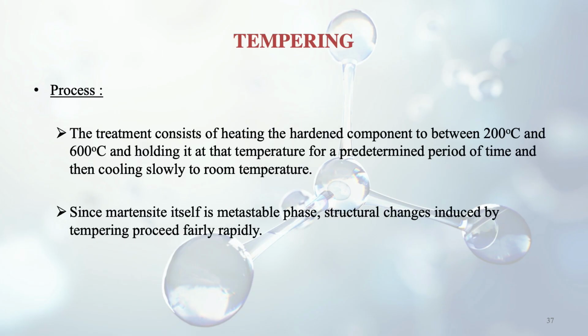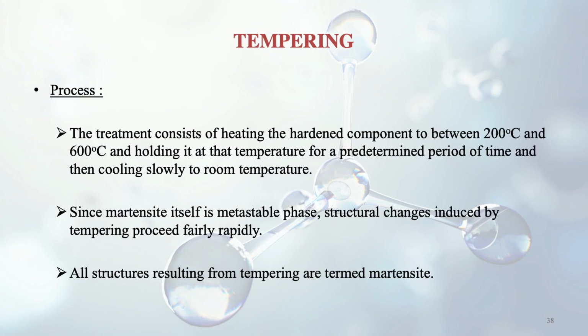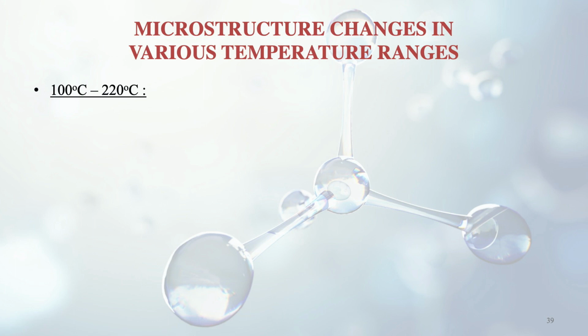Since we know that martensite itself is a metastable phase, structural changes induced by tempering proceed fairly rapidly. It is not a very stable phase, this martensite, so the changes can take place easily because no equilibrium is there as such. And all structures resulting from tempering are termed as tempered martensite. So now we take up what happens in different temperature ranges, what kind of microstructure we get. We will study here, for 100 degrees to 220 degrees centigrade.